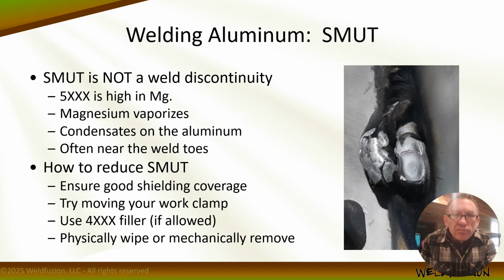If you've ever made a weld on aluminum and noticed a black powdery substance on the surface next to the weld, that's not soot. It's called smut. And that's an official term used to describe this purely cosmetic blemish that can occur on the surface of welded aluminum. That's right. It's not a weld discontinuity, not at all. Instead, it's actually vaporized magnesium condensing back on the aluminum surface due to the differences in melting and boiling point, right? It's most common in 5000 series alloys because those are the fillers that are high in magnesium.